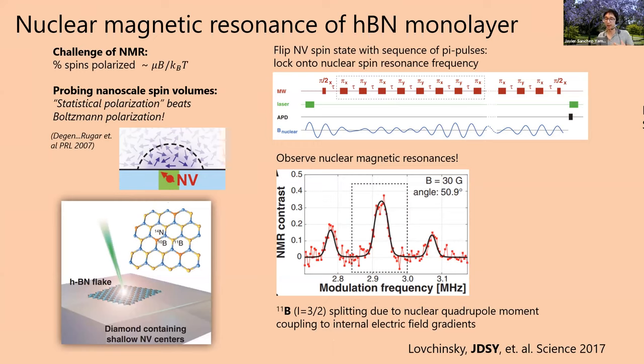The idea is to measure nuclear magnetic resonance in a monolayer material. Nuclear magnetic resonance is where we're trying to measure the magnetic fields generated by the nuclear spins inside of a material. So boron nitride has atoms made up of boron and nitrogen. There are different isotopes of boron, and those all have a magnetic moment that generates a little magnetic field, which you can detect, and that's what you do in NMR.